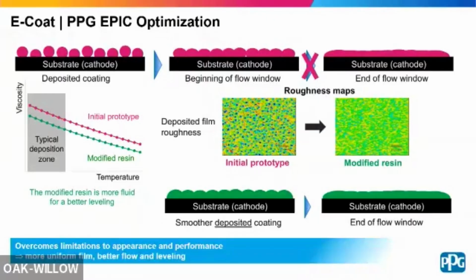So we basically changed how the resin is going to deposit on the film. So we don't want a droplet and then it flows. We want the resin to hit the panel and start flowing, because you're reducing your bake window. You're reducing your bake temperature, which means you're going to start curing this thing a lot faster. So that's pretty much how we address this from the beginning.